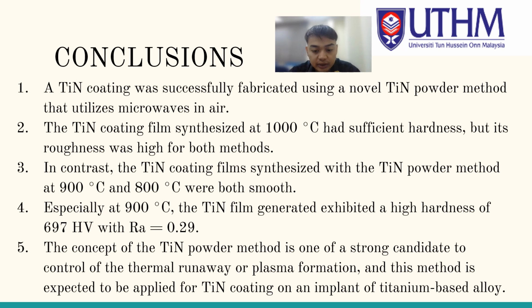For the conclusion, a TiN coating was successfully fabricated using a novel TiN powder method that utilized microwaves in air. The TiN coating film synthesized at 1000 degrees Celsius had sufficient hardness, but its roughness was high for both methods. In contrast, the TiN coating films synthesized with the TiN powder method at 900 degrees Celsius and 800 degrees Celsius were both smooth, especially at 900 degrees Celsius.